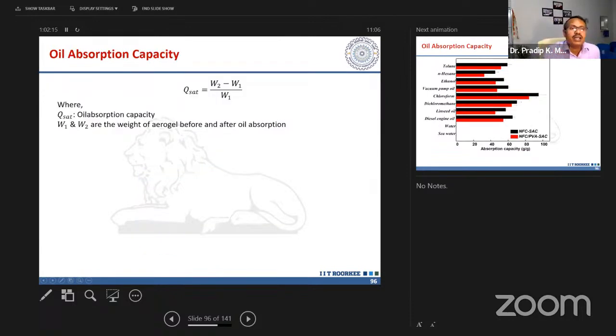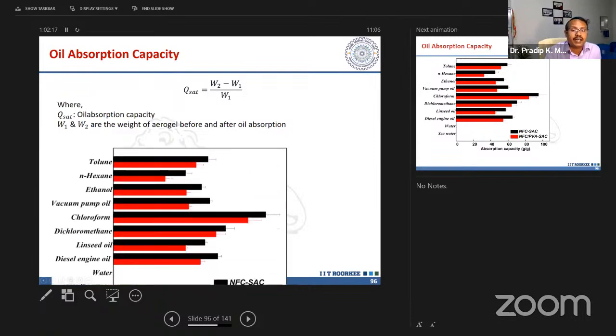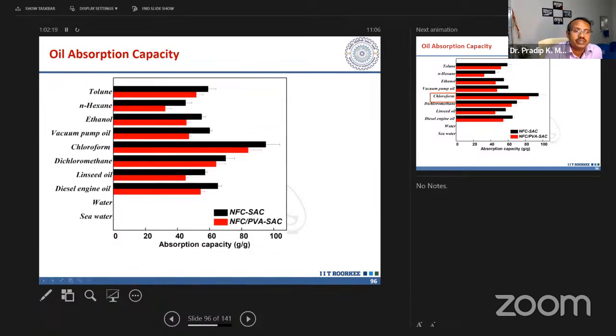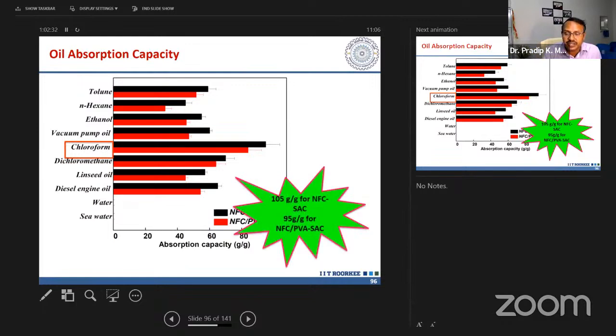We have checked the oil absorption capacity with this equation, and we have checked with toluene, hexane, ethanol, vacuum pump oil, chloroform, linseed oil, diesel engine oil, water, and sea water. We have seen that chloroform is one of the best materials absorbed by this material.